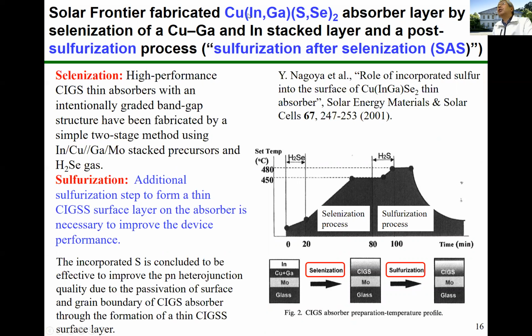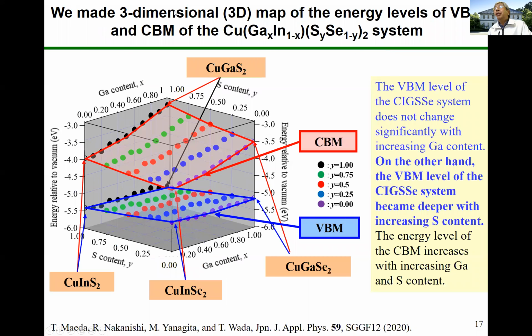Solar Frontier fabricated the CIG(S,Se) absorber layer by selenization of copper, gallium, and indium stacked layers and post-sulfurization process, the sulfurization after selenization, SAS process. A low temperature selenization and high temperature sulfurization. We made a three-dimensional map of the energy level of valence band maximum and conduction band minimum of the Cu-In-Ga-S-Se system. The VBM level of the CIGSSe system does not change significantly with increasing gallium content. On the other hand, the VBM level of the CIGSSe system becomes deeper with increasing sulfur content.